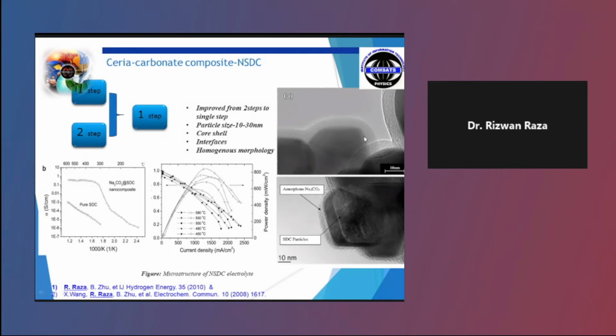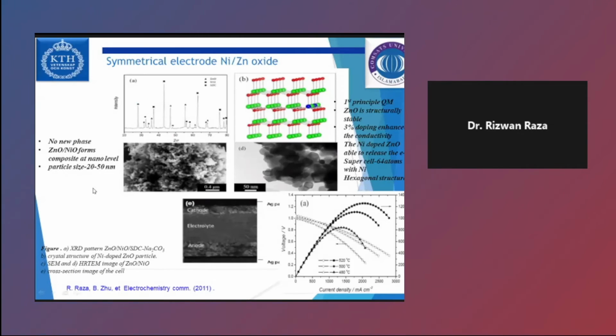After developing this material, it can be seen that the pure SDC, the doped cerium material, has low ionic conductivity at 300 to 600 degrees, but after coating this carbonate on the SDC, it has suddenly increased at this particular range, from 300 to 600 degrees. Ionic conductivity is increased. We have published some similar work in different journals.